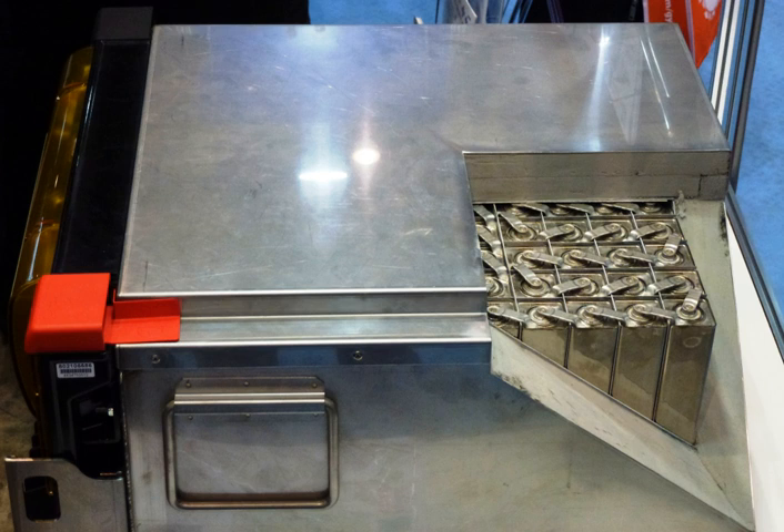In the 1980s, lithium alloy anodes replaced calcium or magnesium anodes, with cathodes of calcium chromate, vanadium, or tungsten oxides. Lithium silicon alloys are favored over the earlier lithium aluminum alloys. The corresponding cathode for use with the lithium alloy anodes is mainly iron disulfide (pyrite), replaced by cobalt disulfide for high power applications. The electrolyte is normally a eutectic mixture of lithium chloride and potassium chloride. More recently, other lower-melting eutectic electrolytes based on lithium bromide, potassium bromide, and lithium chloride or lithium fluoride have also been used to provide longer operational lifetimes and better conductivity.